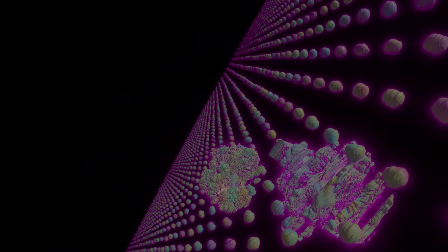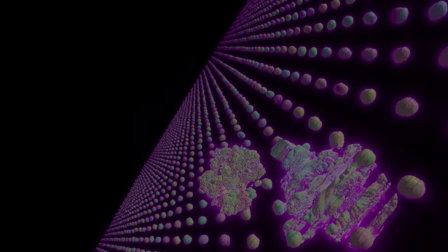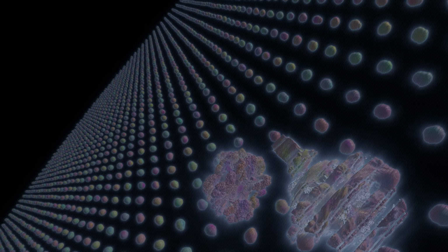Precisely. If you measure a material's phonon dispersion, you learn so much. The number of branches tells you how complex the unit cell is. The slope of the acoustic branches near k=0 gives you the speed of sound directly. The size of the energy gap between acoustic and optical branches tells you about the strength of the bonds holding the atoms together. That LO-TO splitting we mentioned.